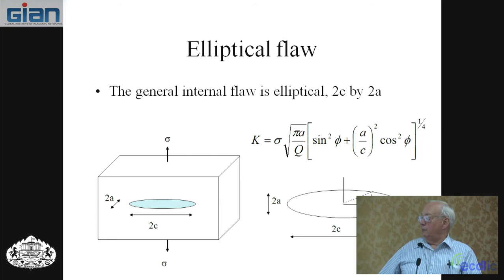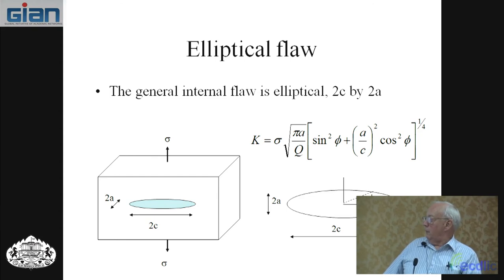Again, you can see this is mode 1. It's pulled, load stress perpendicular to the crack. So it has the form sigma square root of pi a, and there's a Q factor here, and there's also a little phi factor. The phi is the angle from the horizontal. So as phi is 0, that would put you right here. And as you get to 90 degrees, you would be right there. So the K itself changes as you go along the crack front in an elliptical flaw.